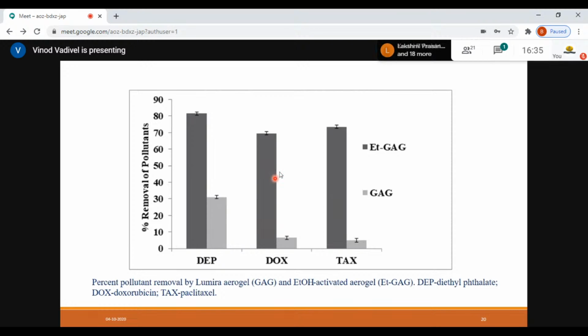And this graph is where I wanted to explain a bit. When I spoke about the aerogel as such, you can see the adsorption of these three pollutants. DEP is diethyl phthalate. Phthalates are microplastics, very commonly present in wastewater. Dox is doxorubicin, one of the chemotherapeutic drugs from hospital waste effluents, and paclitaxel. These three we started with to give an initiation, and we found that when you use the aerogel as such, the adsorption is very low. The removal percentage is hardly 30 for this, 10%, and hardly 5% for paclitaxel.